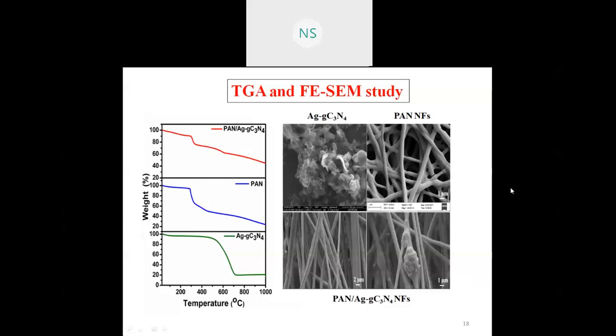The second image is of pure PAN nanofiber. The third and fourth are of polyacrylonitrile silver grafted carbon nitride nanofiber. These materials are decorated over the surface. In the fourth image, there is a fiber of very high diameter, a single thread showing a very high diameter. This is because of the system during the process. Maybe there was a fluctuation in the voltage, and because of it there was a formation of a knot. But all fibers can be observed to have a very uniform size and length.